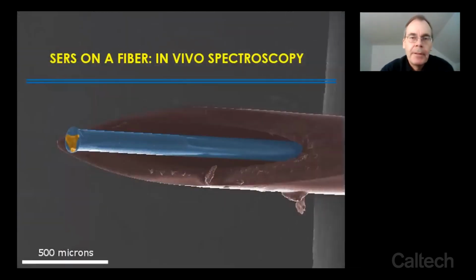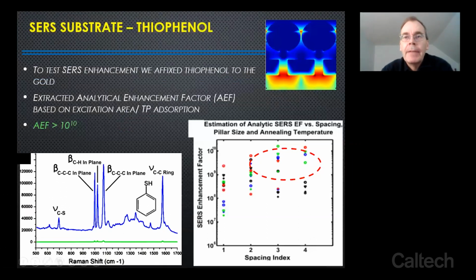We put these on top of the end of optical fibers. The fibers are about the diameter of a human hair, 150 microns or so in size. And this is the surface enhanced Raman spectroscopy field up here. And then that allows us to shine light into it, the laser light. And then it allows us also to extract the scattered light back out and measure it with a spectrometer. So this is a system that when you put it into this injection needle, it allows you to measure real-time chemistry in vivo. And so the high fields are generated and you can measure different compounds.